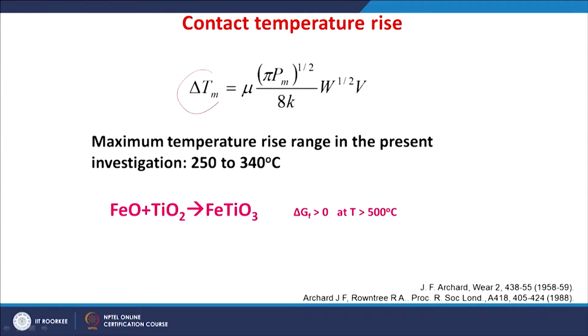So, analytically these were studied by a formula, and very importantly the formula used by Archard shows that the change in the flash temperature is a function of the load and the stress, the load and the speed, and the thermal conductivity, and also the friction. So, the more the friction, the more the temperature increase at the contact for a given material and for a given sliding wear condition.